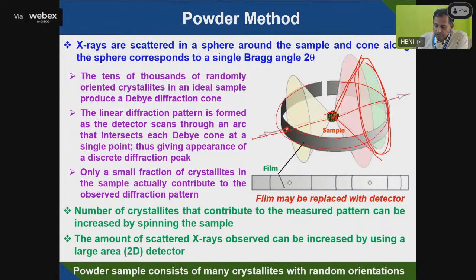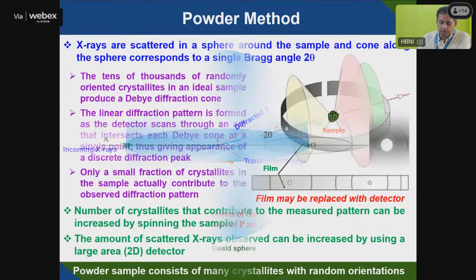Since the sample is here and the X-ray is going, thousands of randomly oriented crystals fall in this X-ray beam, and since it's polycrystalline, you will be able to see many cones. Depending upon the 2 theta value, you will see different angles, different cones. Only a small fraction of crystallites diffract, and the diffraction planes go out. This is the entry hole and the exit hole. This is the ring that is formed on the film.